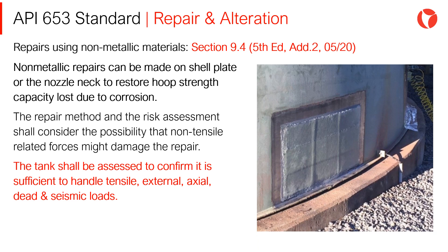Non-metallic repairs can be made on shell plates or the nozzle neck to restore hoop strength capacity lost due to corrosion. The repair method and the risk assessment shall consider the possibility that non-tensile related forces might damage the repair. The tank shall be assessed to confirm it is sufficient to handle tensile, external, axial, dead, and seismic loads.